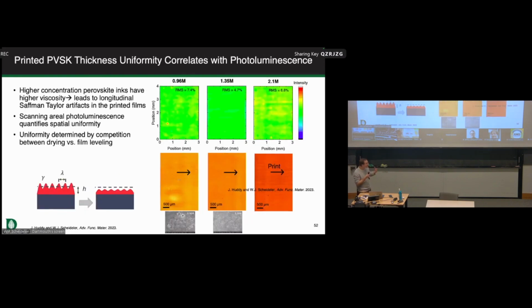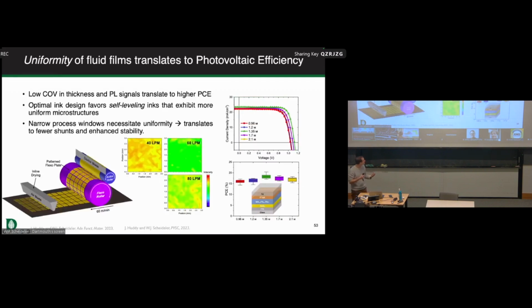Now, the reason we care about that for perovskites in particular is that there's a pretty narrow process window. So we'd like to form a dense grain morphology that doesn't essentially allow any pinholes where you could have shunt current flowing. This is how you make a really efficient solar cell, is preventing any shunts that add to the dark current but don't give you photocurrent. You can map that essentially with an areal photoluminescence. And the message from all this really is that if you want to make a good solar cell, you have to print a really uniform film. If you do that properly, you can make devices that have an efficiency that's on the order of commercial silicon.